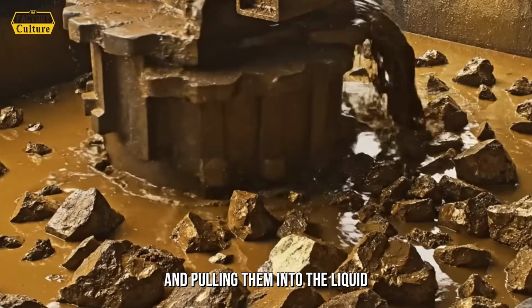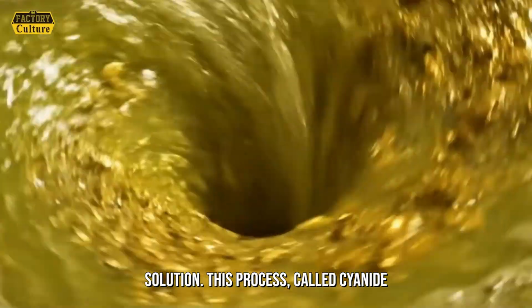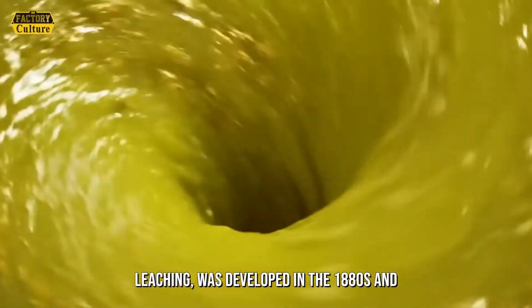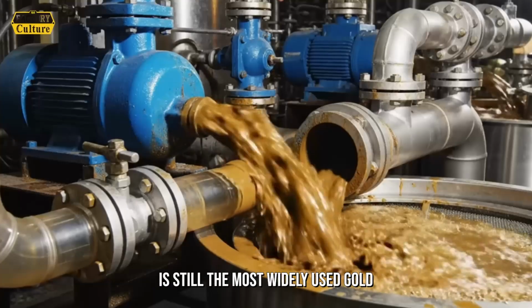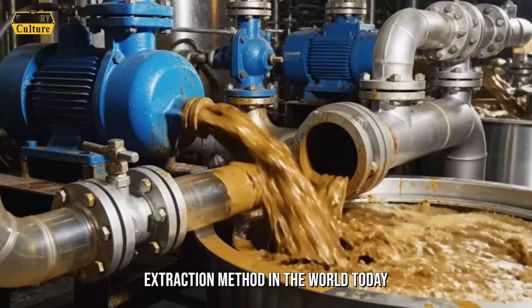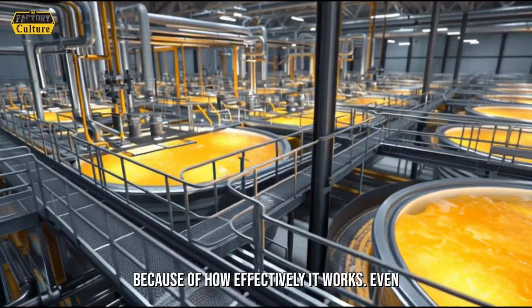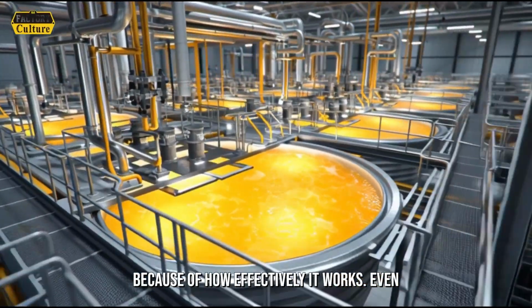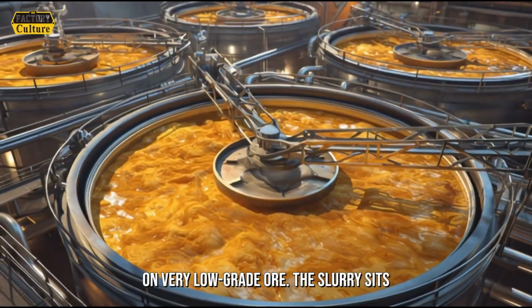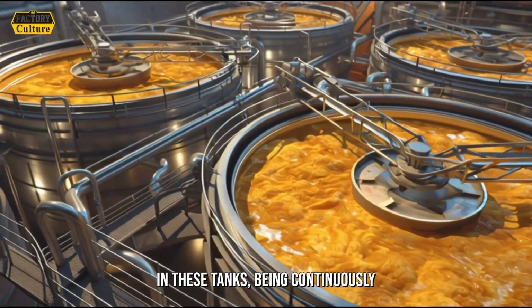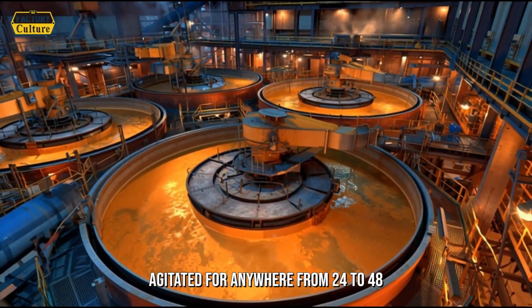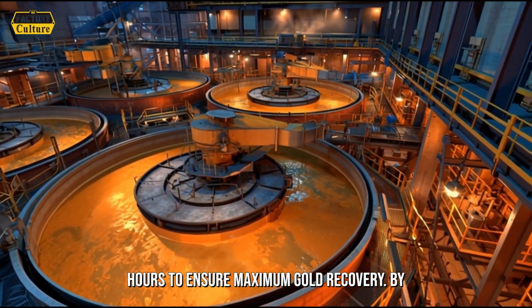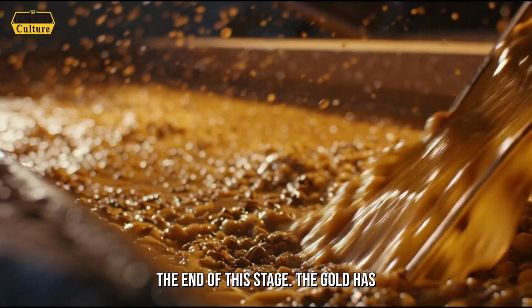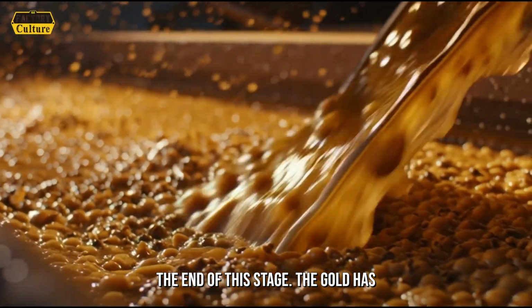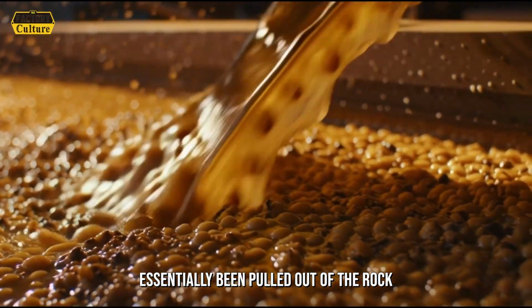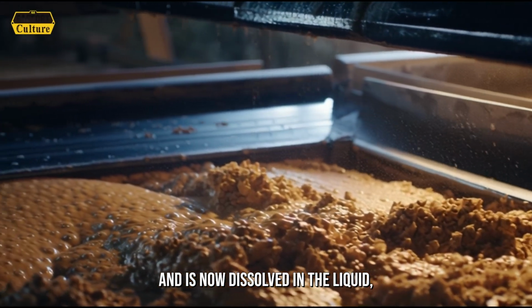into the liquid solution. This process, called cyanide leaching, was developed in the 1880s and is still the most widely used gold extraction method in the world today because of how effectively it works, even on very low-grade ore. The slurry sits in these tanks, being continuously agitated for anywhere from 24 to 48 hours to ensure maximum gold recovery. By the end of this stage, the gold has essentially been pulled out of the rock and is now dissolved in the liquid. Invisible, but there.